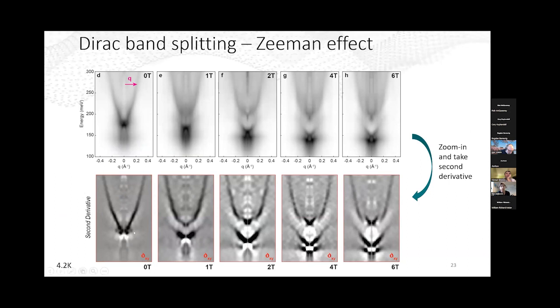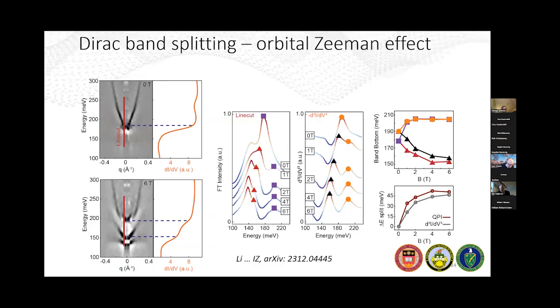It's essentially taking the second derivative. So what you will see is that this single band actually splits into two, and becomes more and more prominent as you increase the magnetic field. And this splitting is actually quite substantial. What I want to show you is there are several ways one can quantify this splitting. One is from the simple dI/dV spectrum, how it changes as a function of magnetic field from one peak to two peaks. This is what I'm showing here in this dI/dV second derivative, where one peak splits into two.